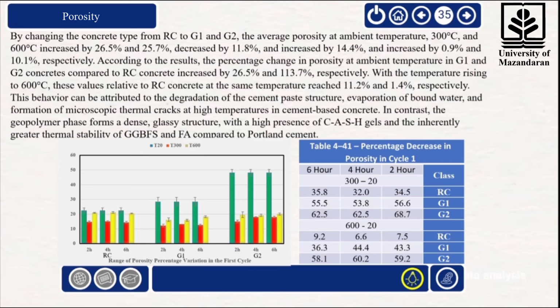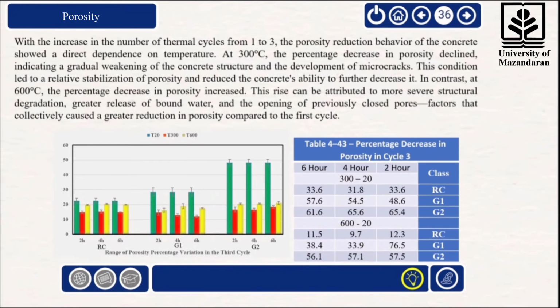The table corresponding to the first cycle shows that the highest porosity reduction occurred in G2, while the lowest was recorded in RC, with G1 showing intermediate performance. With the temperature raised to 600 degrees Celsius, porosity reduction decreased in all specimens. When the number of thermal cycles was increased from 1 to 3, porosity reduction showed a clear dependency on temperature.